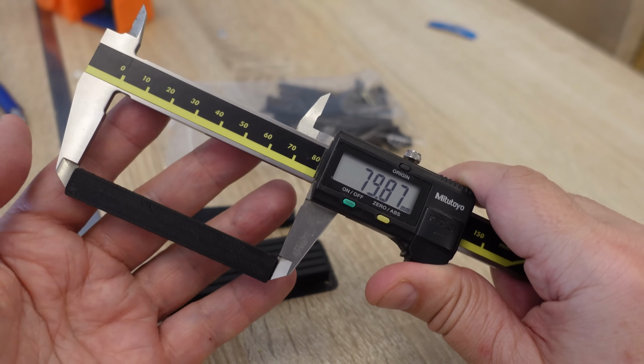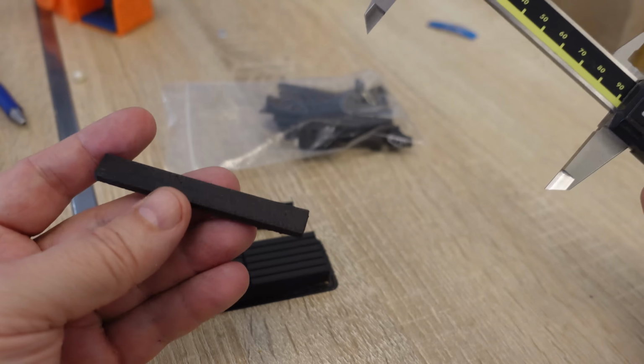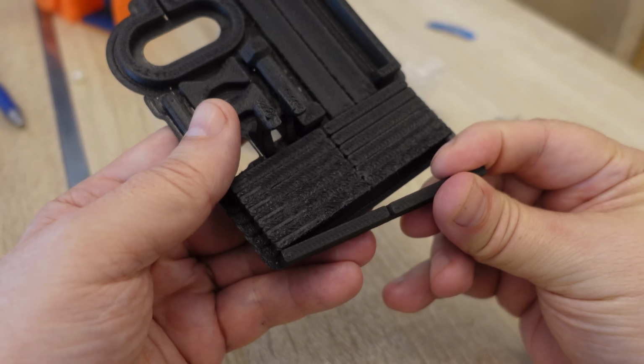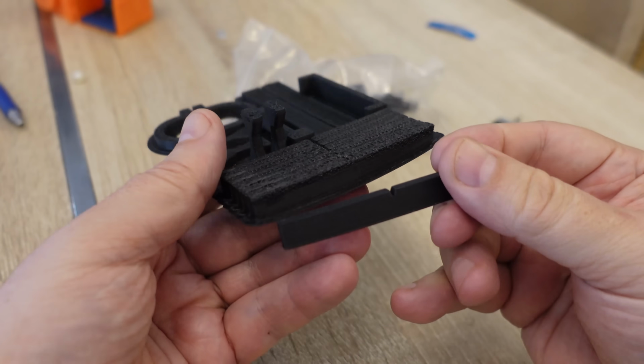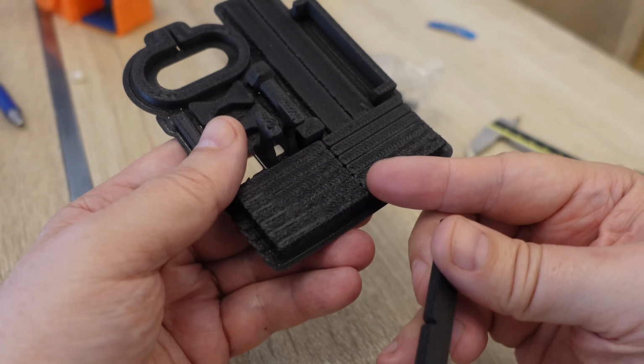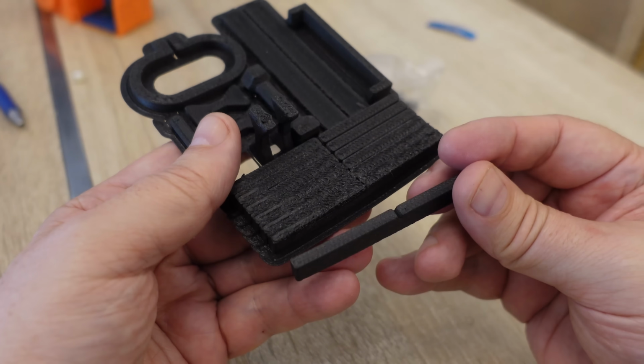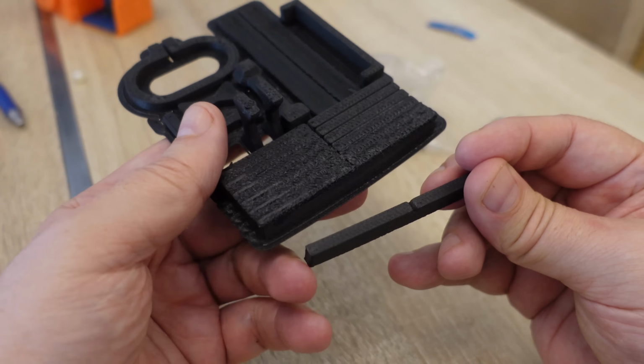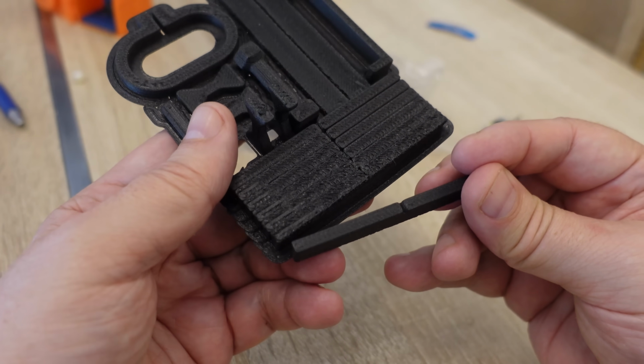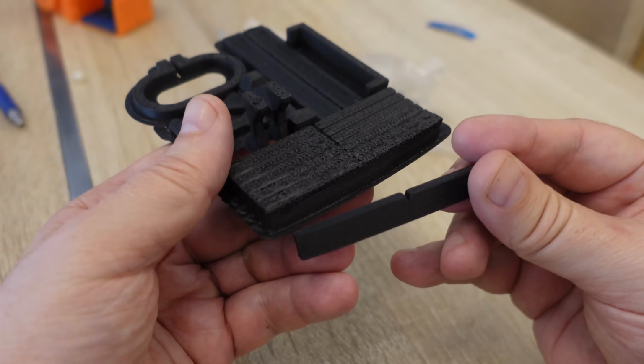Definitely much smaller shrinking compared to the average nylon. Carbon fibers helps a lot. And I have the feeling that without carbon fibers, this filament wouldn't even be printable on these printers. And one more time a reminder how important is the drying. So this was printed after 12 hours on 85 degrees Celsius. And these are my final objects after additional 8 hours on 85 degrees Celsius.